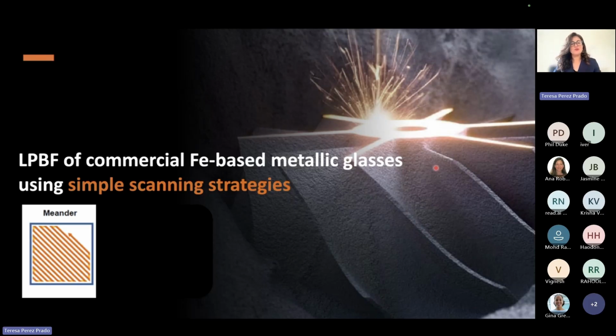But bear with me. So we start from the beginning. At the beginning, there were a few commercial alloys, and this is where we started. I'm going to focus, of course, on the work done by our group on process optimization. And we said, let's start from the beginning. We don't know how these materials are going to respond to LPBF. We are going to use simple scanning strategies at the beginning, and by simple, I mean this meander scanning strategy, so just going back and forth along the cross-section of the sample we are printing.